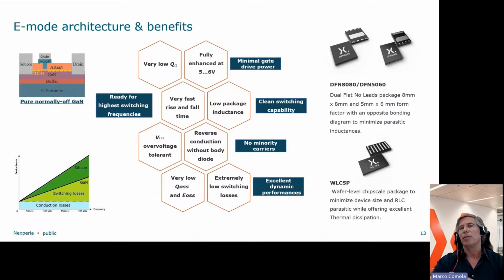And in that case, you have an appropriate bonding diagram used, just to minimize the parasitic effect coming from the inductance and resistance coming from the bonding. Or a package like a chip scale package, and also in that case you have a very low RLC parasitic, and you have also an excellent thermal dissipation, thermal performance. And what else? For the GaN E-Mode, of course, in reverse conduction, there is no body diode, so the reverse recovery is close to 0. And you have a very low output capacitance, output charge, and so very low switching energy in the output, and extremely low switching losses. So you have excellent dynamic performance using the E-Mode.